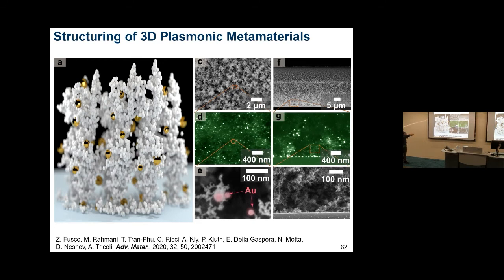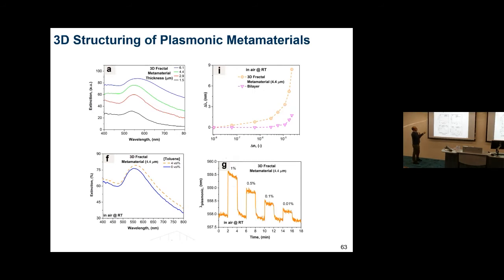This is some SEM images where you see the gold particles, both top view and cross-sectional view, and we can actually identify them. When you use this approach, we create a three-dimensional metamaterial, and here you can control the thickness and the optical properties.